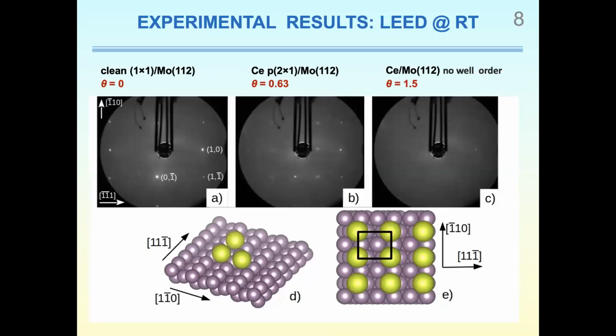During cerium deposition fulfilled at room temperature, the LEED patterns evidence the formation of a predominantly two-dimensional overlayer with primitive 2x1 structure from the early stage of adsorption and throughout the submonolayer coverage range. Deposition of submonolayer amounts of cerium resulted in the appearance of additional half-integer order diffraction spots along the 1,1,-1 direction. The real space model interpreting primitive 2x1 LEED patterns is presented below.